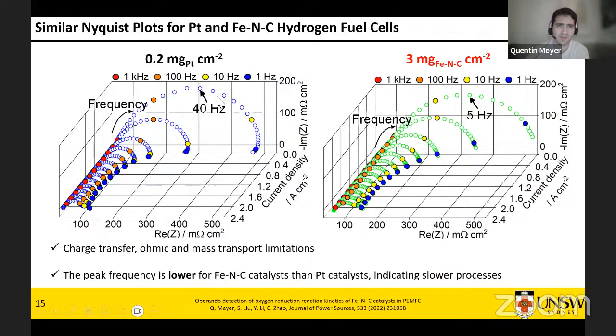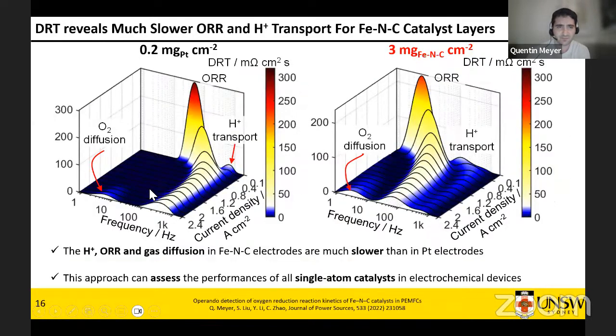And so what I've done is I've taken every single one of these graphs, calculated the DRT, and then used a bit of MATLAB to interpolate the data. And this is what I got. As I said, this is directly the same information contained in my impedance measurement. So proton transport, ORR, and gas diffusion: platinum on carbon, something quite classic. When I look at my Fe-N-C catalyst, it's somewhat similar, but there is a big shift towards lower frequency. So proton transport issue is one peak.